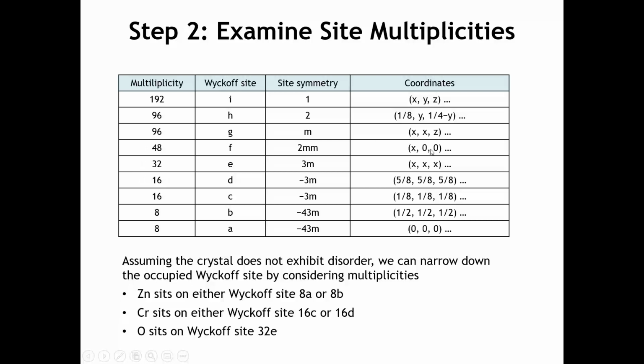And here, while we do have an unknown, those sites are on the threefold axes that go along the body diagonal. So their position is not precisely fixed, just anywhere on that threefold axis, which also has a parallel mirror plane. So we will still have to determine X. But we've made a lot of progress.